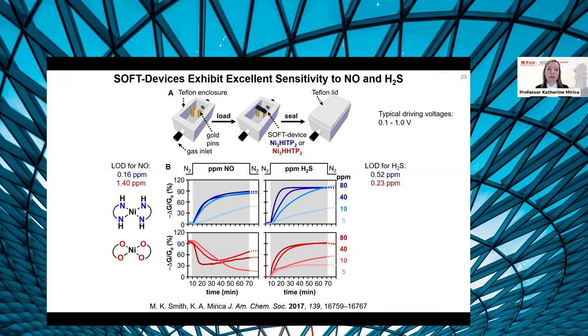Second, we also see differences in the directionality of the response for different materials. So the material in red becomes basically more conductive, so decreases its resistance in response to nitric oxide, whereas the material in blue responds in the opposite direction. In response to H2S, both of these materials respond in the same direction, increasing their resistance in response to this reducing gas. So the material in red is acting like a typical P-type semiconductor, but the material in blue may be a mixed type or more of an N-type semiconductor, which is consistent with some other studies that others have shown for the properties of this material.